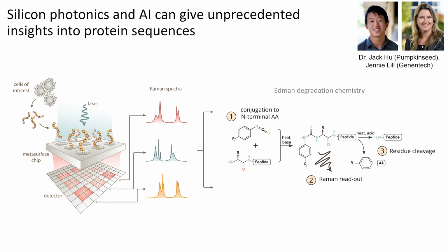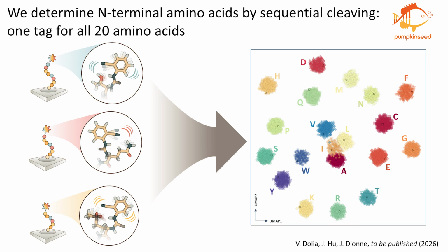And we've engineered those Edman reagents in such a way where they infuse Raman peaks into the protein or peptide spectra that are very specific for which N-terminal amino acid it's bound to. So we have cyclic chemistry. And again, using some of those MD and DFT calculations that my lab worked on, we've been able to engineer these Edman reagents where they still do the cleaving, but they have Raman cross-sections that are extremely bright compared to any of the native amino acids. And then in conjunction with the chip that gives an 8 order of magnitude Raman enhancement, we can do high-throughput single-molecule Raman spectroscopy and protein sequencing.